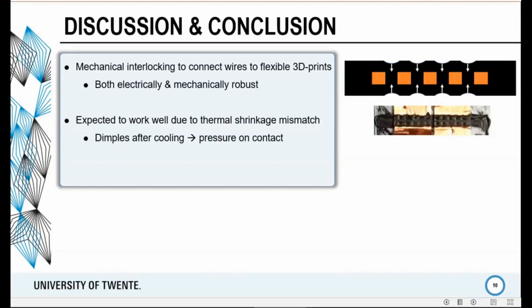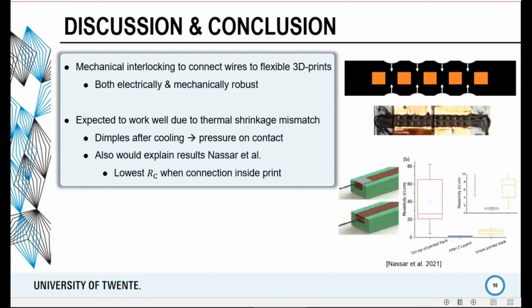One of the indications we got for this is that when we print only 1 or 2 layers of TPU on top of our contacts, then you can really see after cooling down these dimples form in the surface, because it shrinks a lot. And what we could find in literature is that Nassar et al. did tests on electrical wires where they put them underneath the sample, inside of the sample, and on top of the sample. And really the cases where they put the wires inside of the samples gave the lowest contact resistance. So really putting your wires inside seems to be the best option for this.